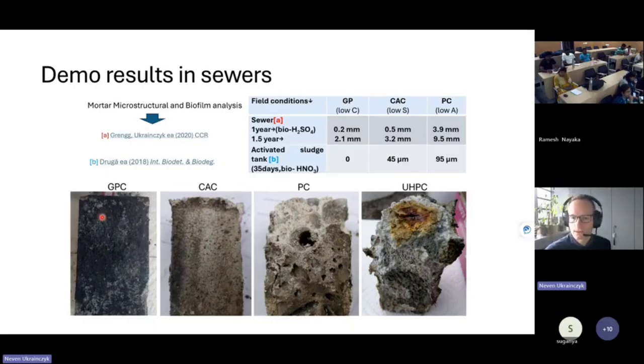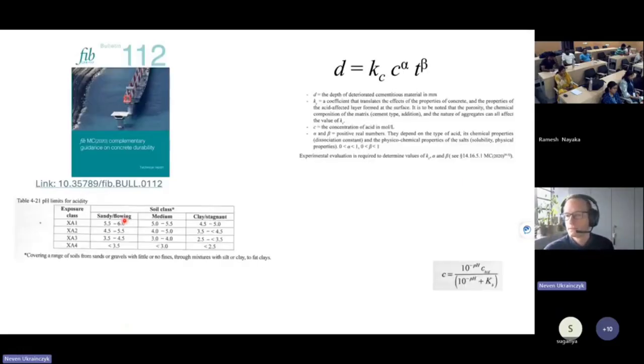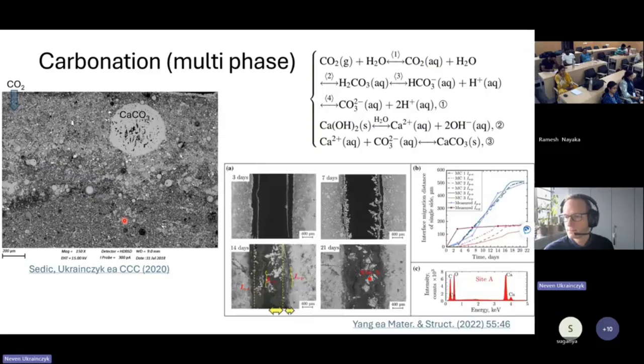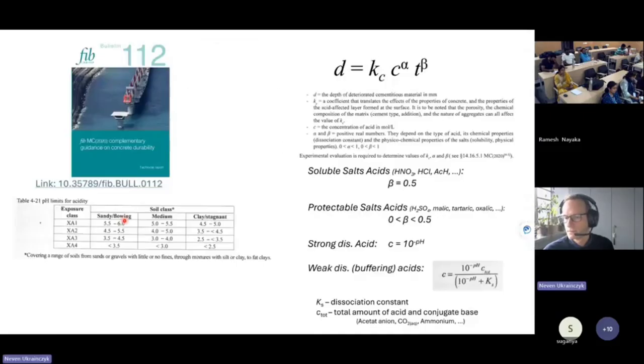We also tried with zinc oxide, but I think only geopolymers, if you design them well, because you need to know how to design a good geopolymer, probably with alkali activated materials. We did just pure geopolymers without calcium, but if you add some slag in it, that would also improve the durability. Because the more calcium you have, the more soluble you make it, but it's also less porosity. I have this slide somewhere, but I will go to it later.